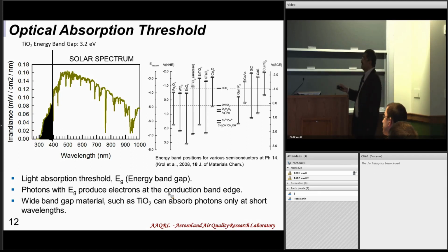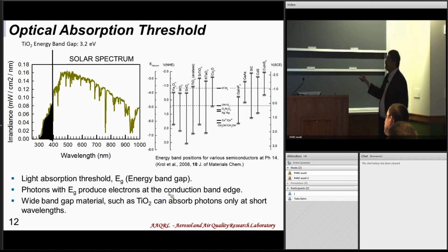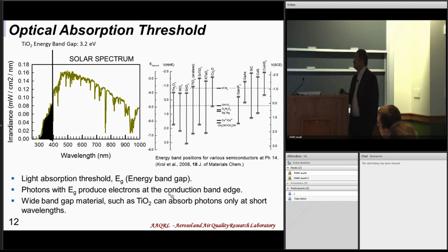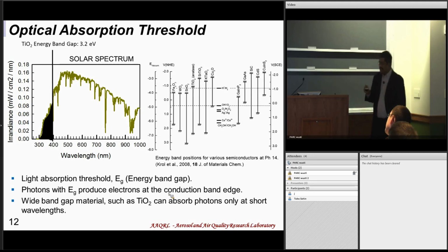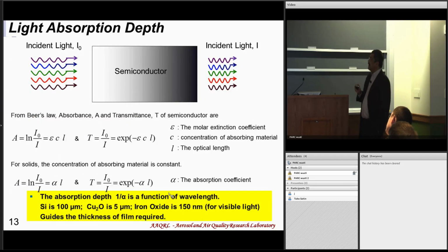So the light absorption threshold, silicon has a smaller band gap than TiO2 and is somewhere here. But again, you can see that there's a large spectrum of the longer wavelengths that are really not harvested in most of the semiconducting devices. So I need to address that somehow. So that's the first thing, is how do I choose my material, or if I choose it, can I do something to enhance the light absorption over a broader spectrum. So that's one thing we keep in mind.